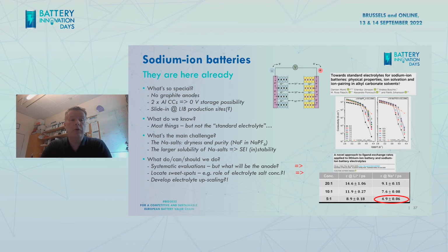To locate sweet spots, even if you have a standard setup of a liquid electrolyte, the role of electrolyte salt concentration absolutely doesn't need to be the same as for the lithium-ion battery chemistry because of the solubility issues. That is something that we looked quite a bit into, to see how, for instance, highly concentrated electrolytes can work, and where you can have ligand exchange mechanisms that are quite different from lithium to sodium, and might also give you hints why the sodium-ion batteries give so much better power performance rates.